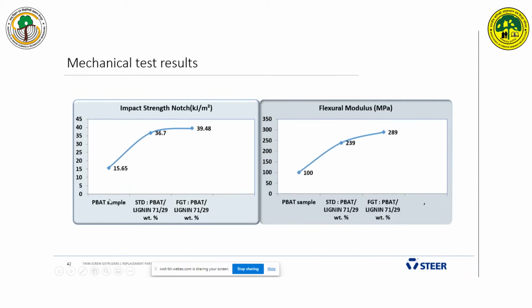When you compare the impact strength, we observed 15 kilojoules per meter square for the virgin PBAT sample, the standard technology showing us 36.7, but FGT is giving better impact strength. But here also, if you see the wood composite, when you added PBAT, there is a reduction in the impact strength. But in the case of lignin, there is an increase in the impact strength.